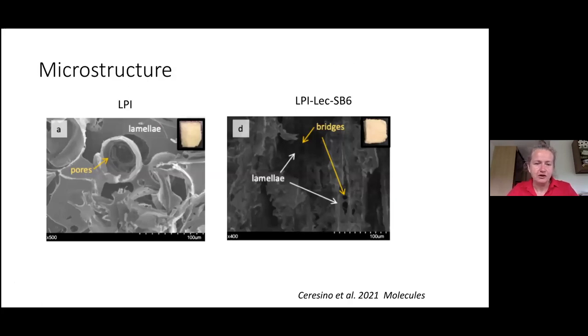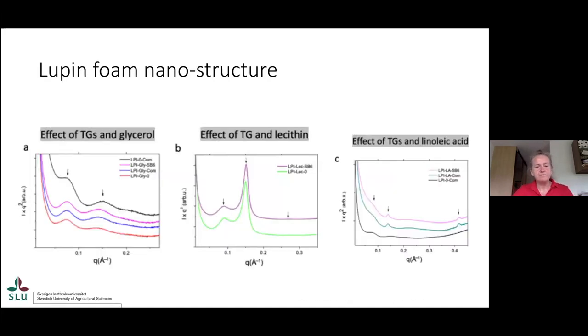With the scanning electron microscopy, we were able to see that the structure was extremely fragile. As you could see, it's a bit messy image in case A, but we were able to distinguish the pores, the lamellae, as well as the specifically formed bridges between lamellae in the lecithin case. So what we can learn from the microstructure is a certain level of how ingredients together with the proteins interact.